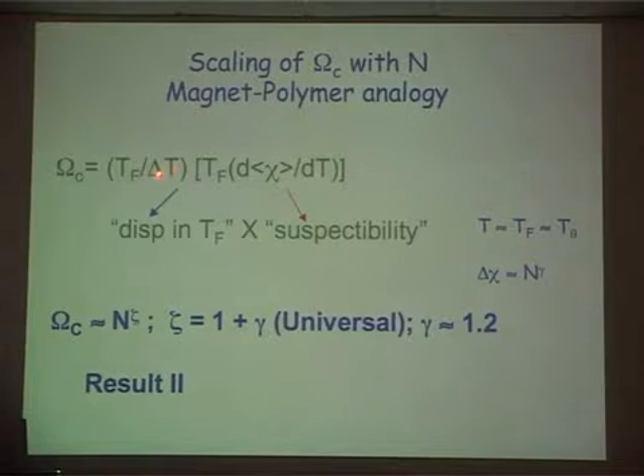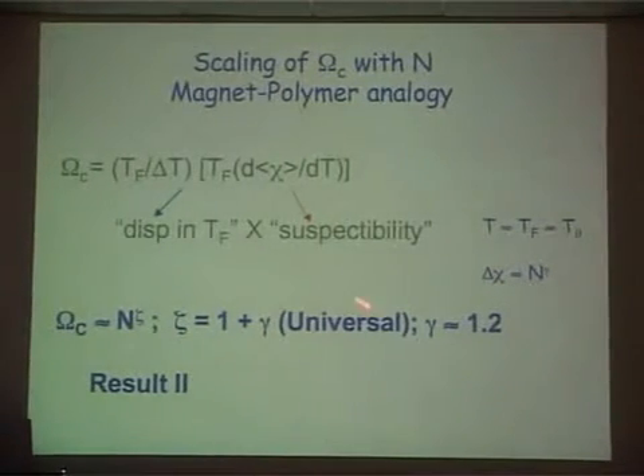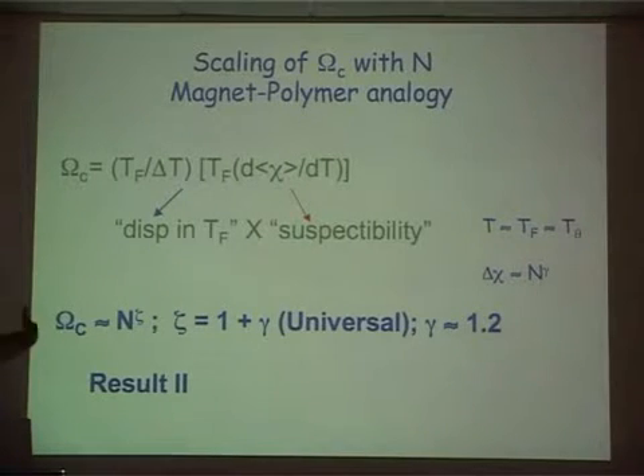This is just TF over delta T, and we showed that delta T over TF is 1 over n, and therefore this goes as n. So this is linear in n. This piece in here is the susceptibility, and if the properties are governed by the susceptibility as you come from above, then they have to be governed by the properties of the polymer chain or the protein chain under good solvent conditions or nearly good solvent conditions. And we know susceptibility scales, again from polymer theory from de Gennes, as delta chi scales as n to the gamma. Gamma is a susceptibility exponent, not the surface tension.